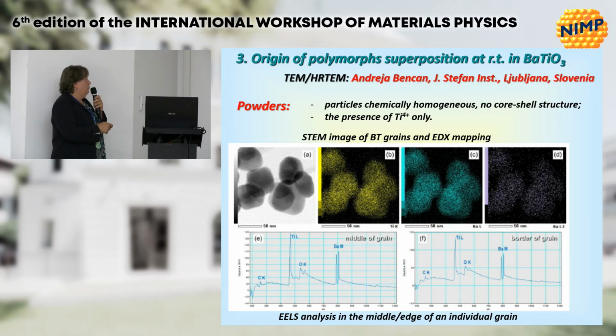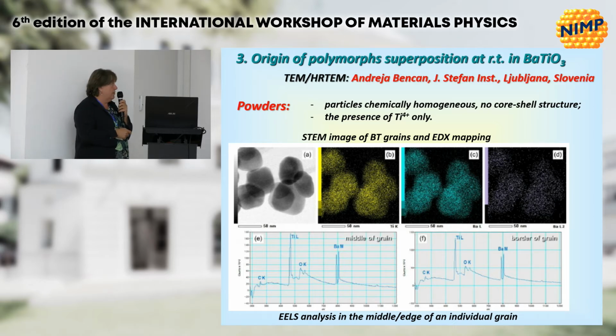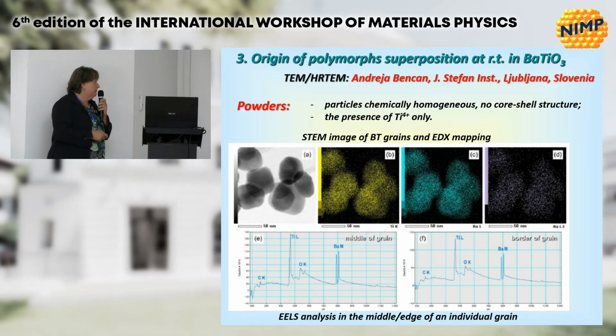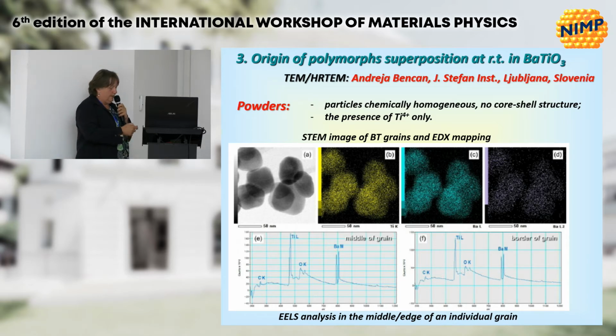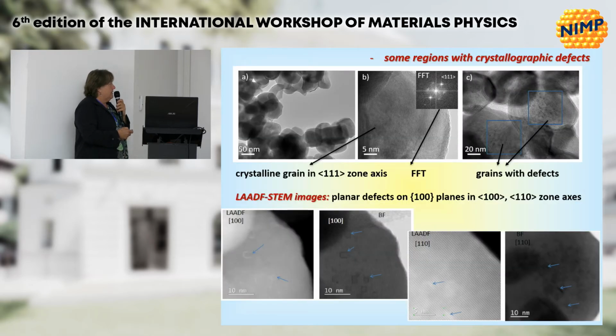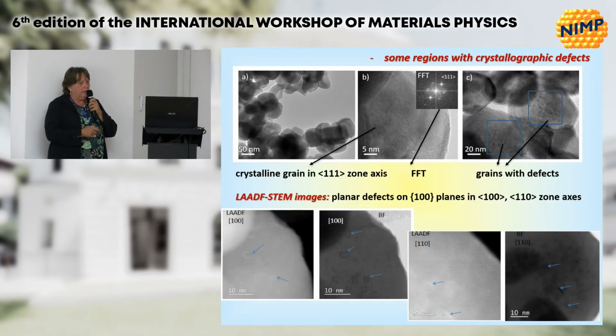So when we try to look at the origin of phase superposition, why we have a phase stabilization with respect to other samples that we have investigated, a high-resolution TEM study by Andreja Bencan demonstrated that we have no impurities, no boundary effects, no segregations. For example, the spectral analysis inside or at the border of grains shows just the same composition, and the presence of titanium only. Usually, hydrothermally synthesized powders may present some internal nanoporosity, which was not found here.